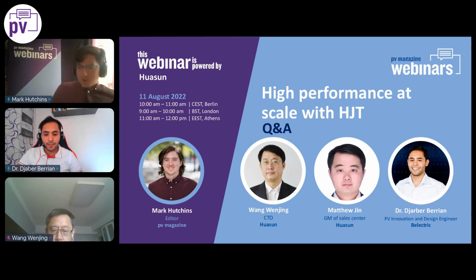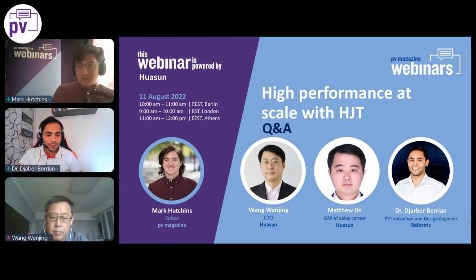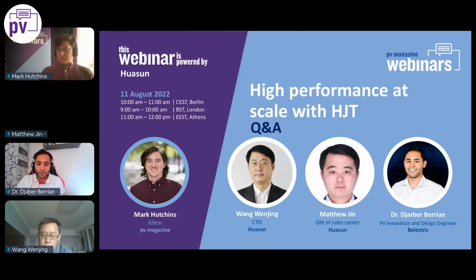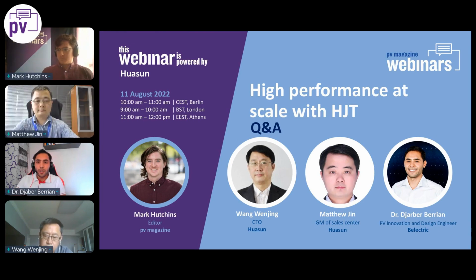First, though, Djarber, one person in our audience noticed that in your case study, the DC to AC ratio was lower for the heterojunction than for PERC. Can you explain why that is? Yeah, I think this highlights the fact that, due to the higher yield and high efficiency of this technology, it makes sense to go with a lower DC-AC ratio, meaning you pay a bit more for inverters but don't compromise the yield. While for the lower efficiency technology, it's better to compromise the yield and pay less for the inverter. So this is exactly what we see here in this lower DC-AC ratio.